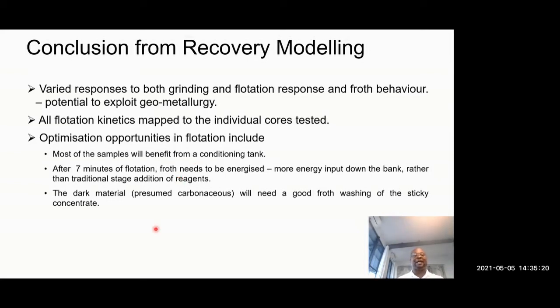Number one. Number two, what you wouldn't see by just sitting back and waiting to do your calculations is that dark material, presumed carbonaceous, will need a good froth washing of the sticky concentrate. That's what we did, and then we were able to get the recovery up. So if you didn't provide froth washing on the circuit, then the day that material predominates, you are going to have a problem.